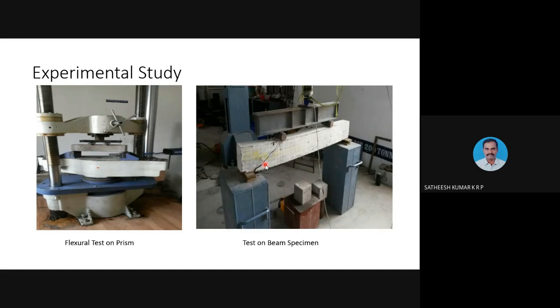And the reason for this kind of failure can be related to the very low tensile strength capacity of this particular material. As I've already said, even for the high molar solutions, the tensile strength of the geopolymer was much less than that of the conventional concrete. And the dimensions of these specimens cast are: this beam is 1.5 meters in length. It had a cross section of 100 mm by 175 mm. And the grade of steel used was Fe415.